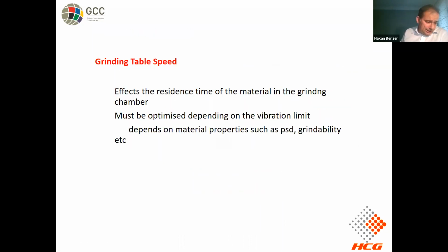And the last effect in the vertical roller milling is the grinding table speed, which affects the residence time of the material in the grinding chamber. And this must be optimized during the operation because of the vibration limit. And this vibration basically depends on material properties such as particle size distribution or grindability of the material.